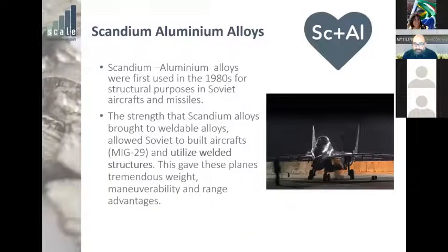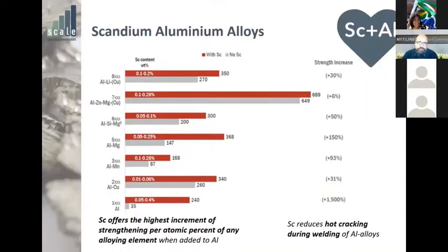More importantly, scandium goes very well with aluminium, and the scandium aluminium lithium alloys have a nice history behind them, since they were used in MiG aircraft back in the 80s, allowing the MiG-29 to use welded aluminium structures, making it much lighter and more maneuverable in the air, giving it a distinct advantage during the Cold War. So what does the addition of a few percent of scandium into an aluminium alloy do?